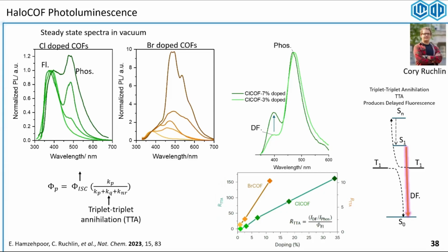As I mentioned before, when you have two triplet excited states and they meet each other, one of them loses the energy down to the ground state, and one of them gets pumped to a high-lying singlet excited state. This singlet excited state can then come back through internal conversion to S1 and emit fluorescent light from S1 to S0 if we have a fluorescent COF. And this fluorescent light is fundamentally different from the conventional fluorescence, because it has gone through two triplet excited states, a bimolecular process, a much longer process. So we see it as a delayed fluorescence.